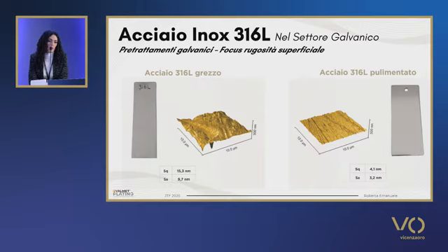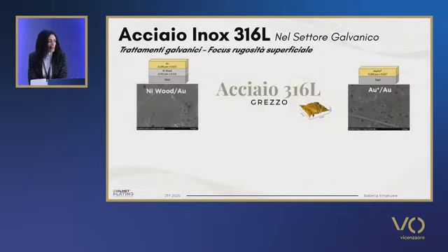We looked at the roughness of two different samples, one of a raw stainless steel 316L, and the other one had been treated. You see the difference between the two samples. One is much better polished than the other one. And the AFM image is very representative. If you look at the data for SQ, the two data are very different.